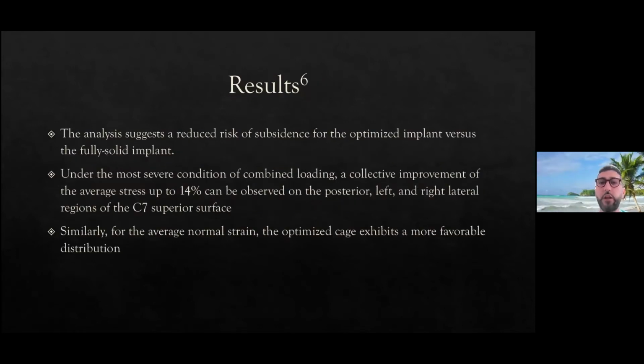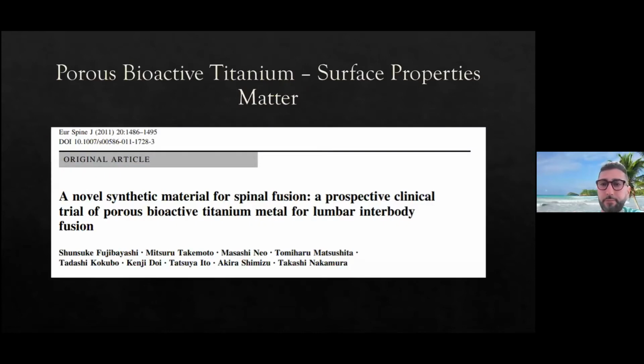And what they found was that there was likely a reduced risk of subsidence for the optimized implant versus fully solid. In other words, they were able to engineer the titanium graft to more closely match the modulus of elasticity of bone. And I've put here the number that they saw a 14% decrease in average stress on these components of the vertebral body. They used a simulated C7 vertebral body, and a more favorable distribution.